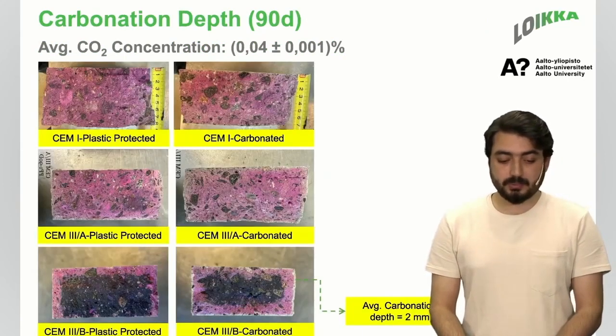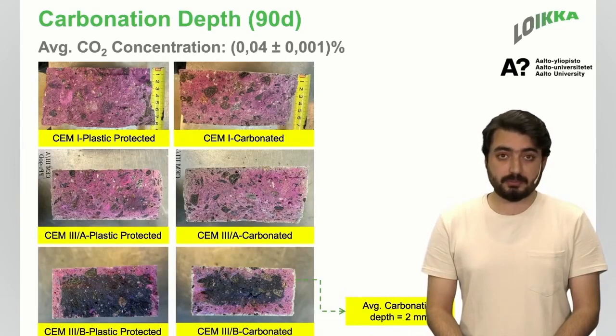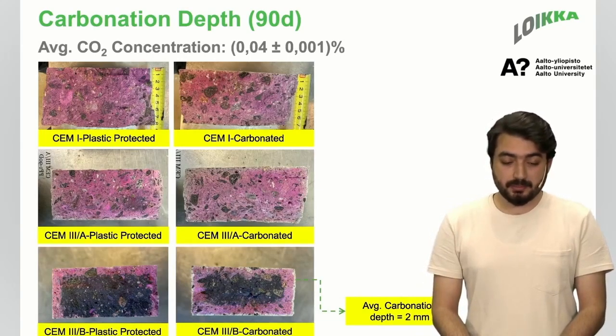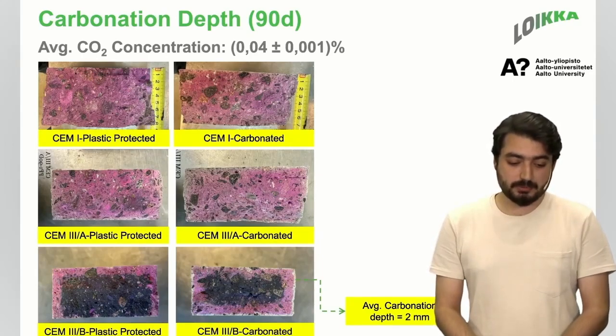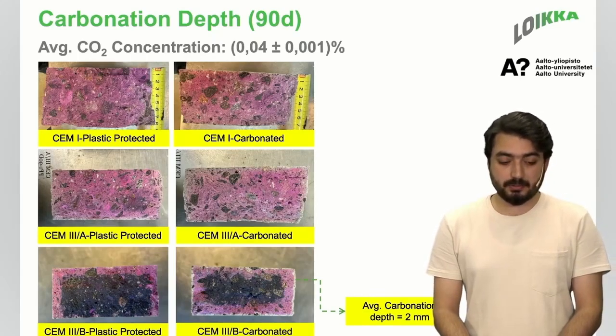Then moving towards the carbonation depth after 3 months, when they were aged and placed in the relative humidity room. So here it is basically a natural carbonation phenomenon, so we are not concentrating anything, but the naturally present CO2 concentration is usually 0.04% in the atmosphere. So here we can see the whole surface that is tested turned pink. I would say it doesn't have any carbonation depth for CEM I, and here we are comparing the plastic protected and carbonated samples.